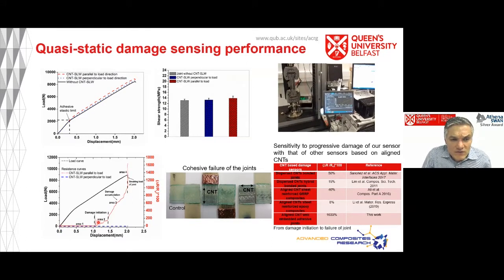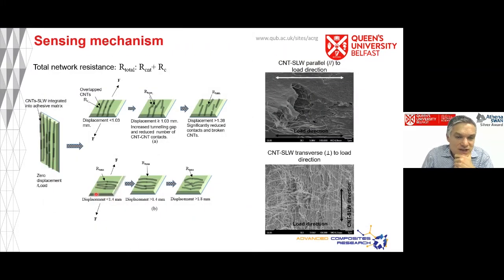Now, I mentioned that we've got the carbon nanotube web also aligned orthogonal to the loading direction, and it's not very sensitive. And the reason why it's not very sensitive is because nothing that we are doing to that web when those nanotubes are orthogonal to the loading direction is affecting the resistance. Now, the change in resistance that we can measure when we load in the direction of the carbon nanotubes is a combination of the intrinsic resistance of the carbon nanotubes themselves. You've got the overlap of the carbon nanotubes, and indeed that resistance also includes tunneling, right? So we know that carbon nanotubes within a very, very short distance of each other can transmit electrons.